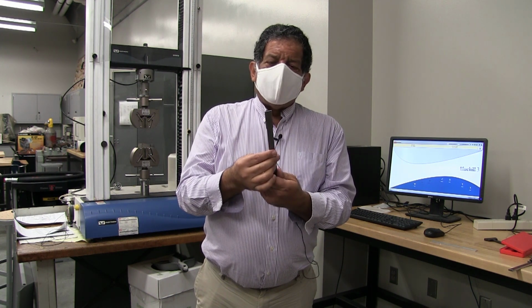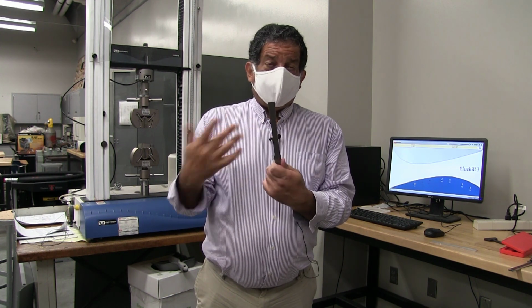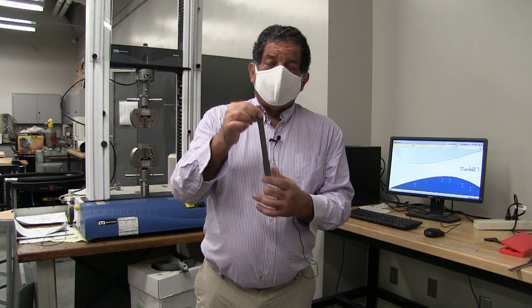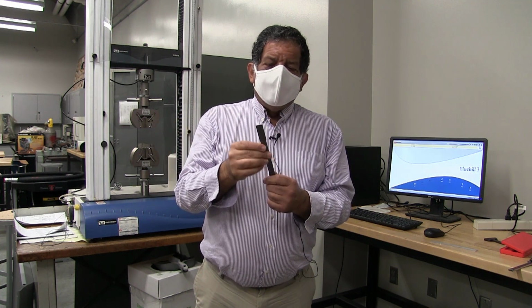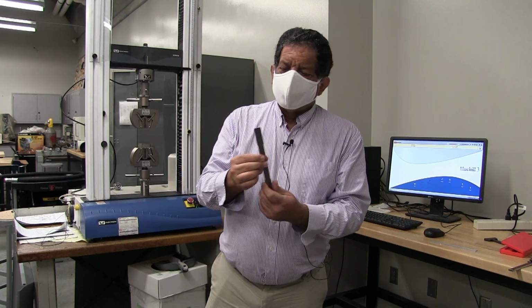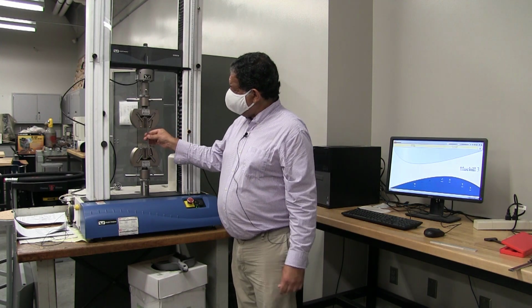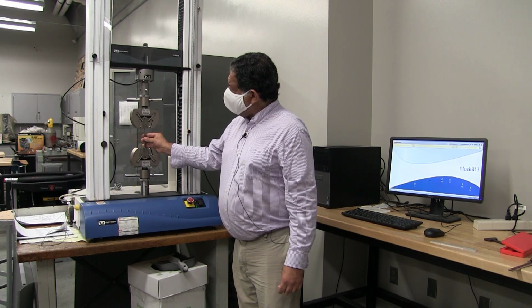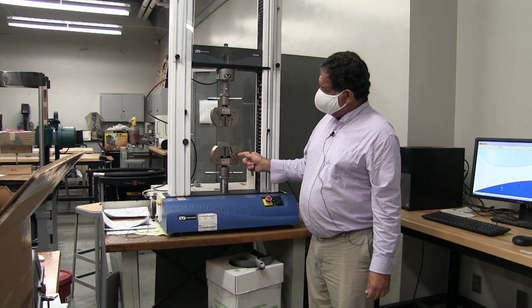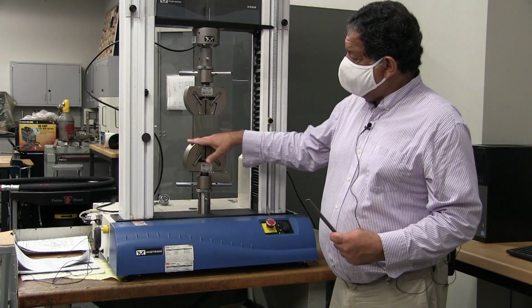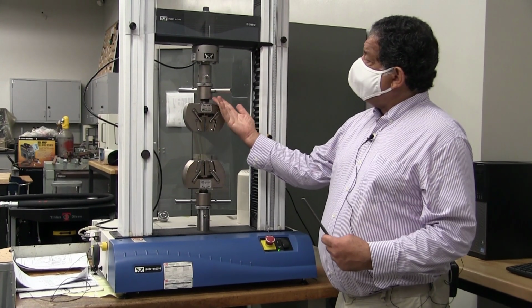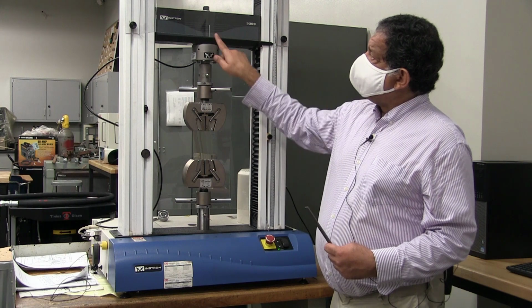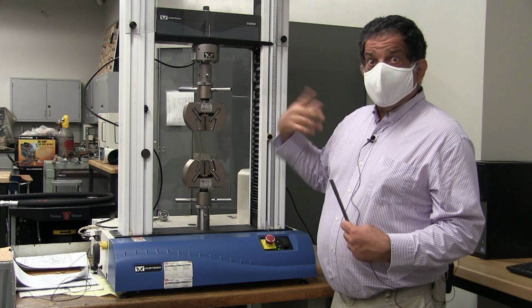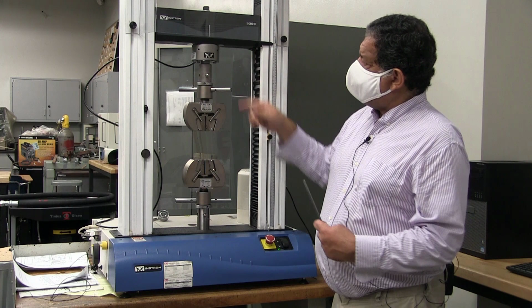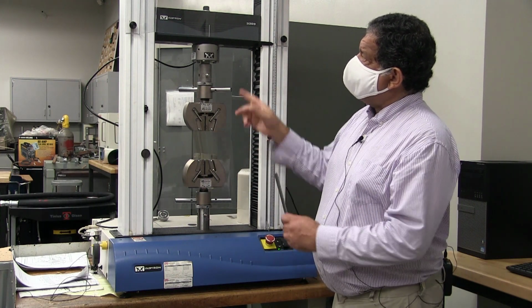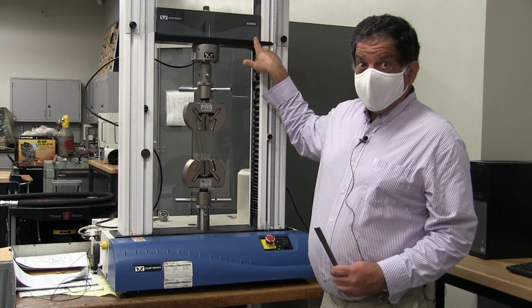That measurement of strain is very versatile in the sense that you can do it all the way until the specimen breaks and it's not a problem, but it's not super accurate. When I put this specimen into the machine over here, the bottom part of the machine is clamped, so this bottom grip is stationary. The top grip travels with the crosshead. So when I turn the machine on, the crosshead is going to travel upwards, and the displacement that is being measured is how far up the crosshead traveled.